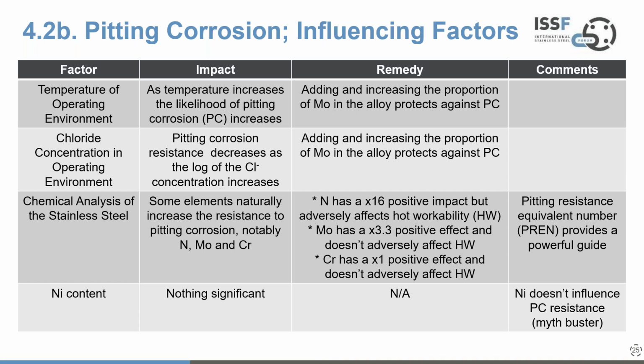So the temperature of the operating environment has an impact on pitting corrosion. As temperature increases, the likelihood of pitting corrosion increases. And increasing the proportion of molybdenum protects against that because it retains that stability in the passive film. And molybdenum is pretty much the key remedy here, because we talked briefly about chloride concentration in the environment. Here the relationship is that pitting corrosion resistance decreases as the log of the chloride ion concentration increases. And again, addition of molybdenum will prevent that problem from occurring.